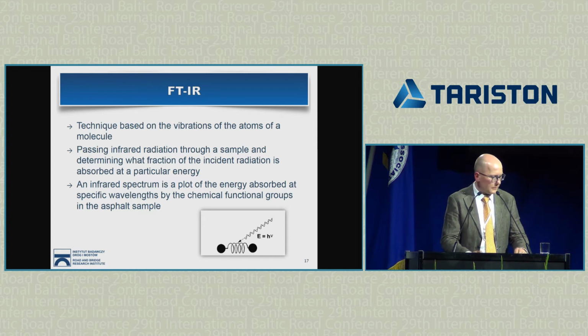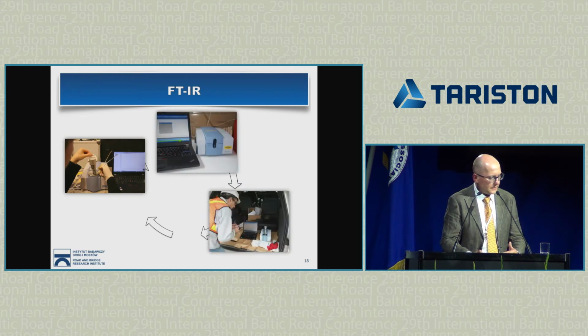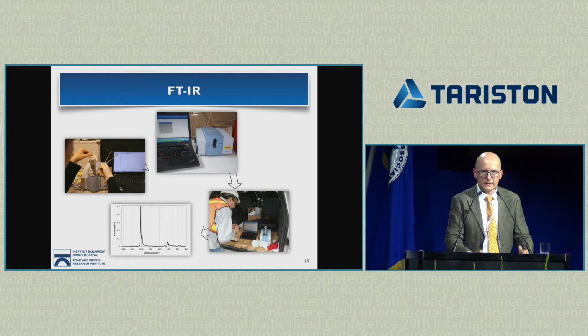So to understand a little bit more how FTIR is measured, you radiate the material with infrared light, where the frequency is controlled by the machine, of course. And then the molecules absorb some of this light. And then on the detector, you can measure how much light was actually absorbed by the material. And then you can plot it in a spectrum. So you will plot the amount of energy absorbed versus the frequency. And in the pictures of the device here, you can see different devices. You can actually do the testing on site, on the construction site, and then at the end you will get a spectrum that is in the lower picture.